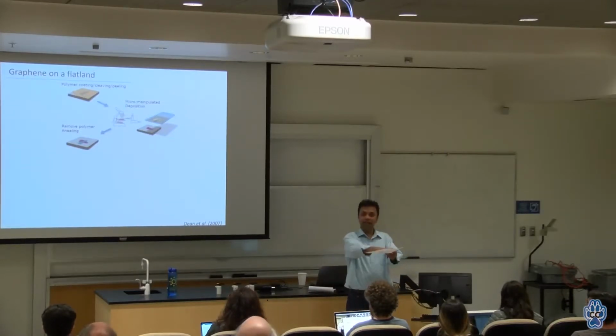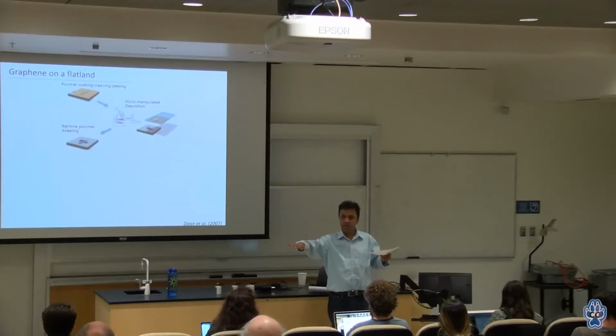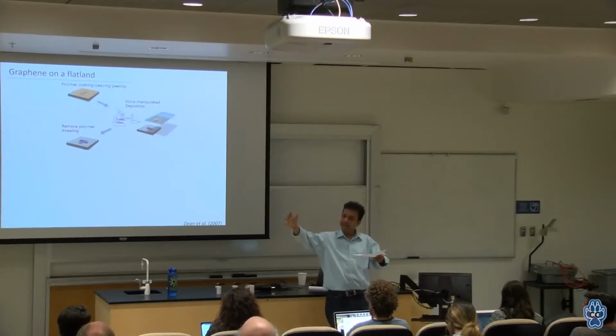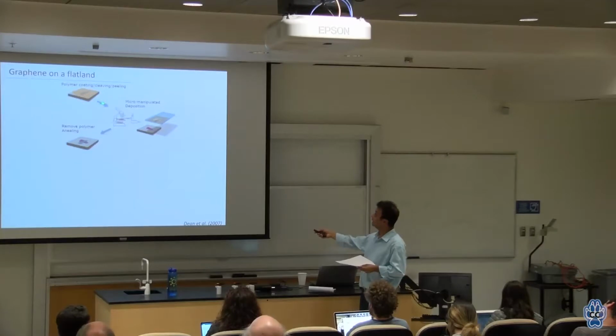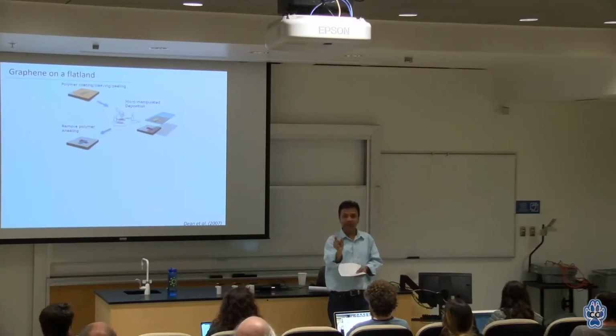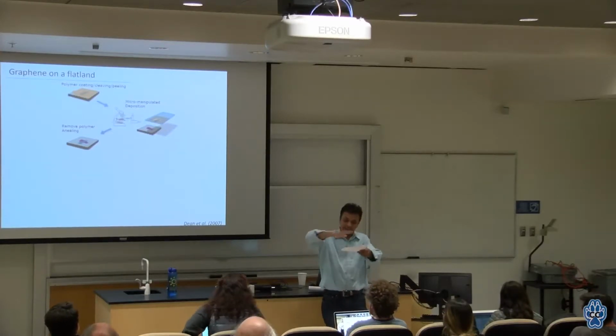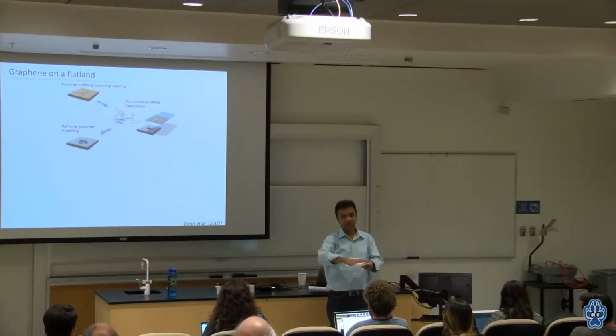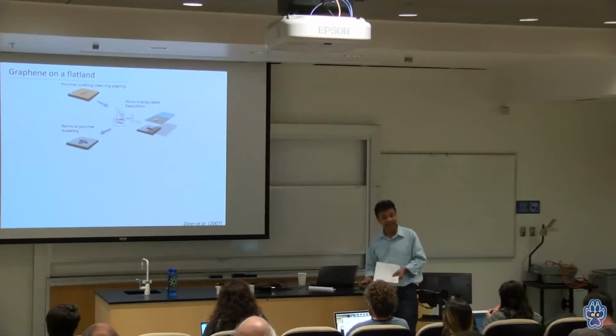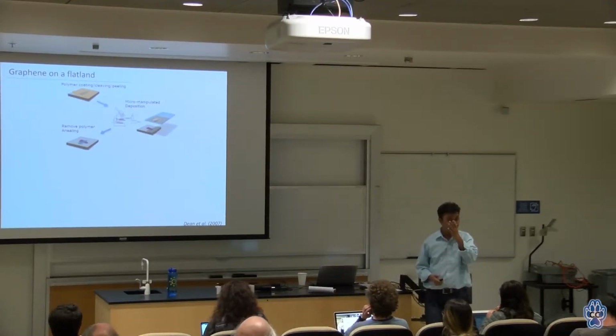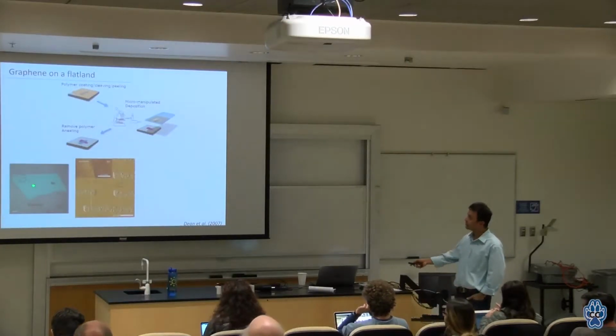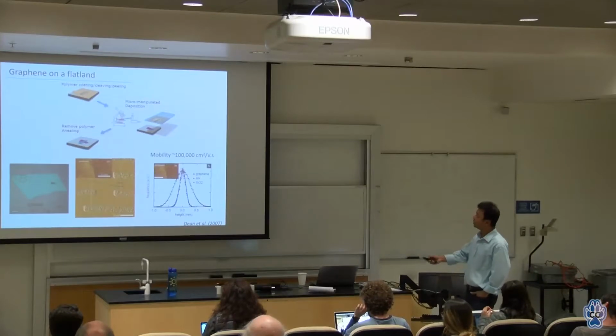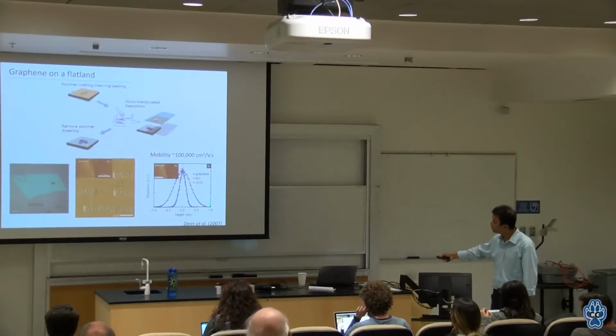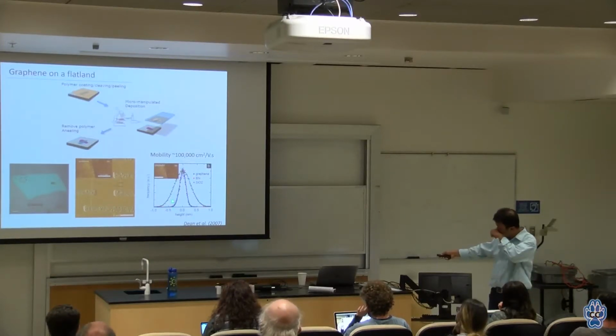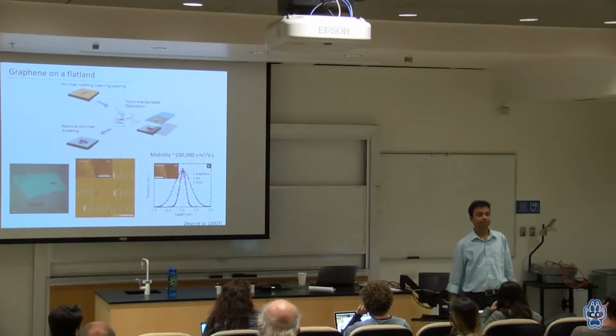So they have graphene here, and they prepare a microscope slide with boron nitride. And under the microscope, think about it, all these materials are a few microns. They align the samples under the microscope and put graphene on top of boron nitride. All right? This is quite challenging because you have to do everything perfectly. Then you can see this is your boron nitride, and on top you have graphene. What you are looking at here is the surface roughness. This is your surface roughness in silicon dioxide, and when you put it on top of boron nitride, it shrinks by an order of magnitude. Okay?